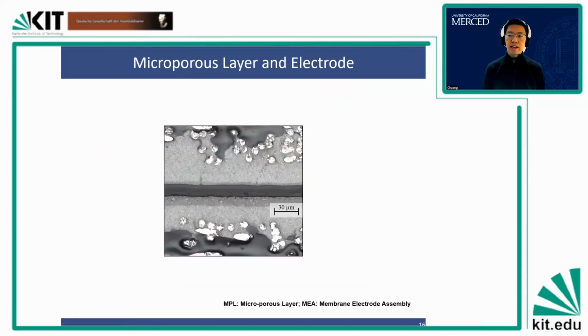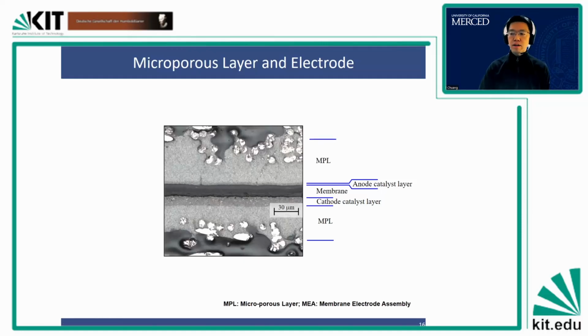Then my second task was to include the microporous layer and electrode on top of the gas diffusion layer. So this is a cross section of a detailed microporous layer, together with the membrane and catalyst layer. Here you have the microporous layer, which consists of carbon powder with PTFE. And then you have the anode catalyst layer, a membrane, and a cathode catalyst layer. Then you have another microporous layer, so it is a symmetric sandwich. One side, on the top, will be the anode side. Hydrogen flows in and reacts here. On the other side will be the oxygen side, so oxygen flows in and reacts with proton and electron to generate water.